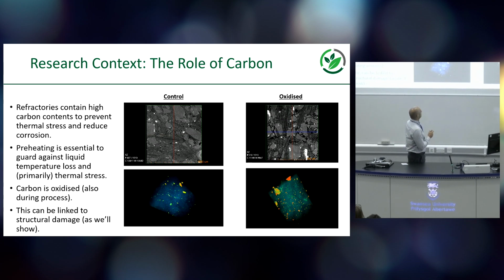And we have used a technique, which I haven't explained yet, so this is a little bit backwards, to look non-destructively at the material. So this is the rocks again, and I apologise, we've now flipped the colour chart, so this is the rocks, and then this is the carbon and the graphite around the sides here. And you can see that if you expose it to oxygen at high temperature, then you will get a certain level of porosity if you do nothing to it, and then more and more porosity as you do. So you damage the material essentially.